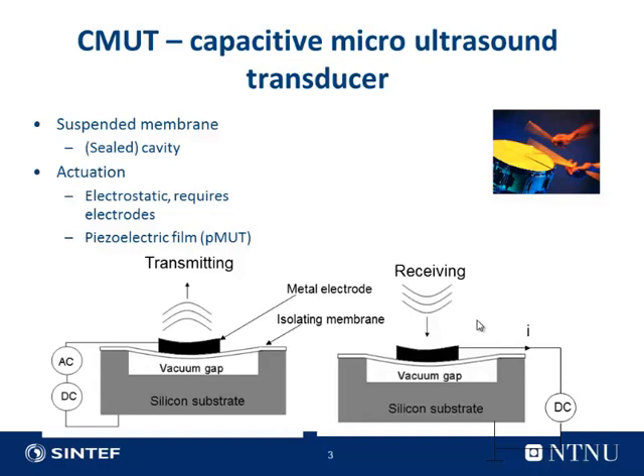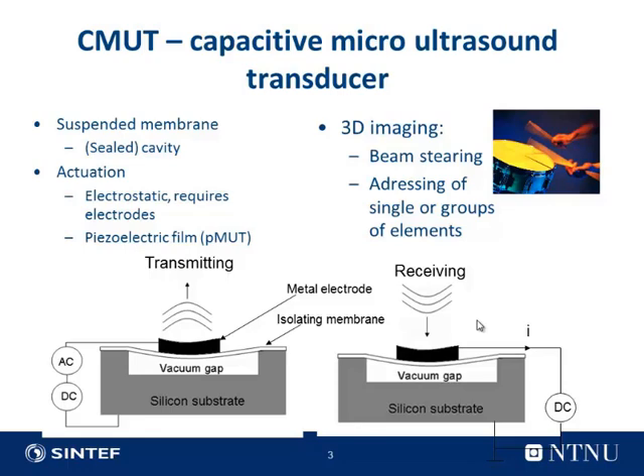Here is a principal view of where you have the metal electrode. This is the simplest CMUT you can make, a metal electrode on top of a suspended membrane, and you just use the silicon substrate as the ground. You apply a DC bias to control some pre-deflection of the membrane, and then the AC to transmit, and then you collect the signal in reception mode.